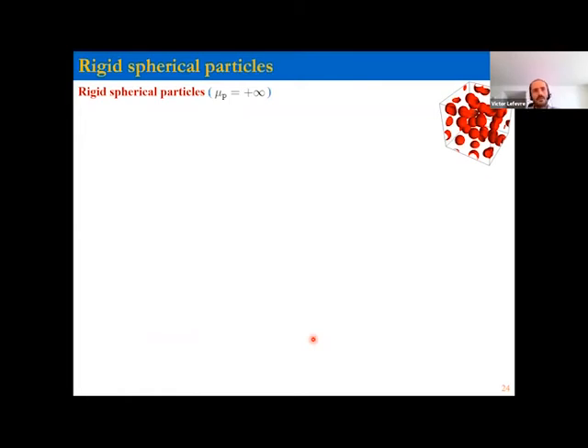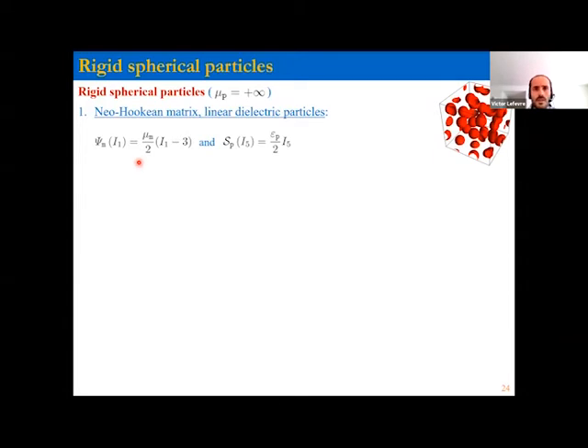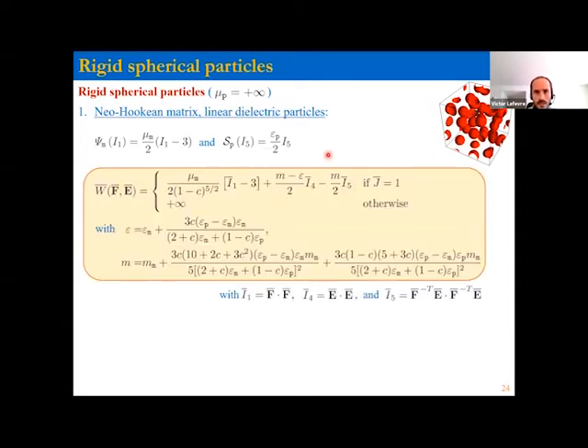All right, so let me look at a more specific problem, the case of rigid spherical particles of a significant practical interest. So first, let's look at the simplest choices for the matrix. So it's going to be neo-Hookean, and for the particles, they're going to be linear ideal dielectrics. So these are the two choices for psi m and sp. And in this case, this complicated formula I showed you earlier reduces to this expression, which is fully explicit, which is very nice.